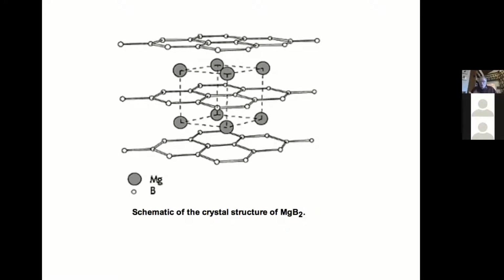And in the Zintl scheme of thinking about things, the idea is that magnesium gives its 2 electrons, 1 electron to each boron, so to speak, and essentially turns boron into something looking like carbon. And so these become graphite-type sheets. Of course it's a metallic compound, it doesn't quite make itself into a semiconductor, but it becomes instead this very interesting superconductor.